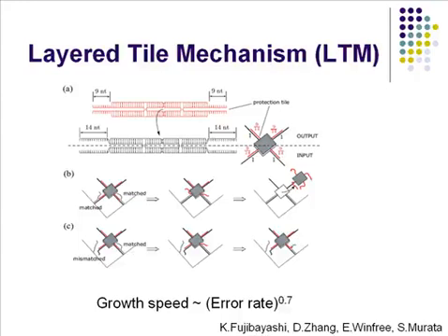The idea is if both of the input sides of the DNA tiles are correctly matched to the structure, as this shows, then those strands are connected to the lattice, and at the same time, the partially covering part of the covering tile is removed by the connection.